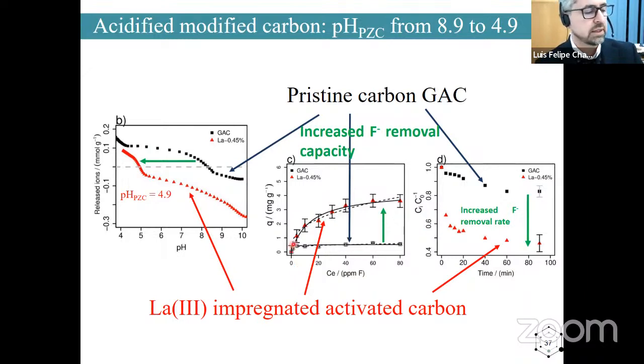So then the adsorption isotherms show that the maximum adsorption capacity of the modified carbon was almost 8 times higher than that of the pristine carbon, according to the Langmuir adsorption model. And you can observe that the modified carbon presented a faster removal, with a more accentuated slope here, compared to the pristine carbon. So the difference is quite clear.